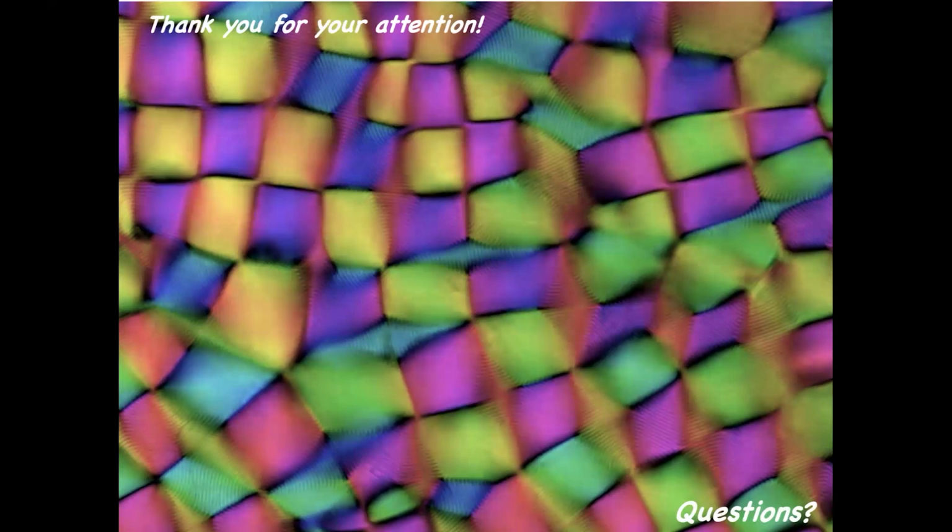So just to cut the long story short, you asked me about the persistence length. Yes, if you're not way below the persistence length, we believe, and we have done some calculations, at least from a scaling point of view, it makes sense. The bending fluctuation of the fiber, which is now below the persistence length but still bending, disrupts the long-range order of the chiral nematic phase, the long-range cholesteric phase. So the persistence length and the bending length are extremely important in governing what you see. You are totally right. Still, it took me a few years to get to that point.